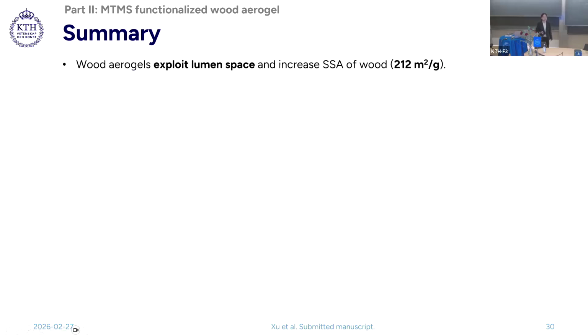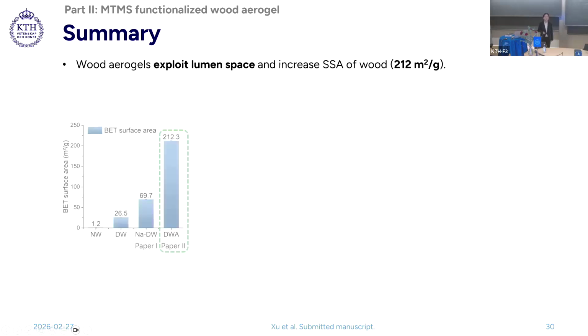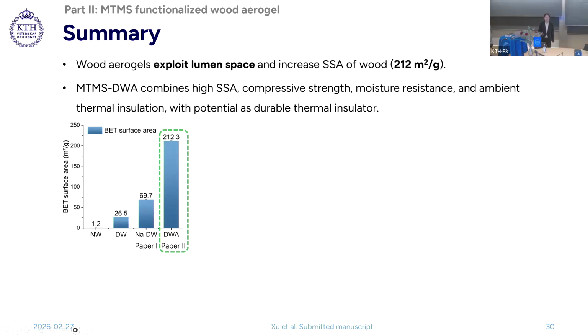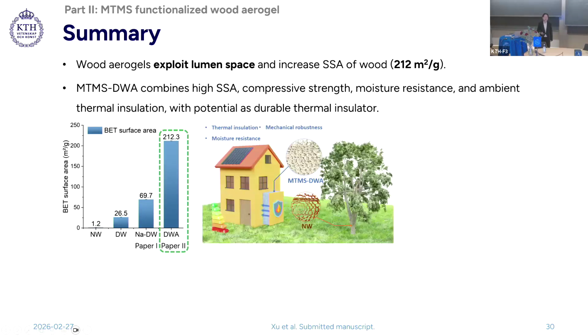In summary, the cell engineering strategy used in these parts, which is extracting intrinsic biopolymers from the cell wall to the lumen to create the wood aerogel structure, effectively utilizes the lumen space and significantly increases the specific surface area, marking a great improvement over the values reported in paper 1. The obtained composite combines many interesting properties, such as high surface area, mechanical strength, moisture resistance, and good ambient thermal insulation, showing a great potential as a durable thermal insulator in energy-efficient buildings.